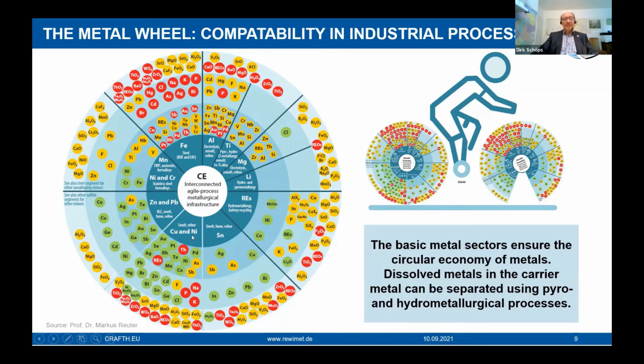of nickel and copper. And here, for instance, you see that there are a lot of green dots, and as well there are a lot of green dots in zinc and lead. And this means that on this route of the non-ferrous metals, zinc, lead, copper, nickel, a lot of metals can be recovered. Not so in the sector of iron aluminium. There you see no green dots. It is very hard to get the recovery of metals in the route of iron production or aluminium production. It is almost impossible to get metals back.